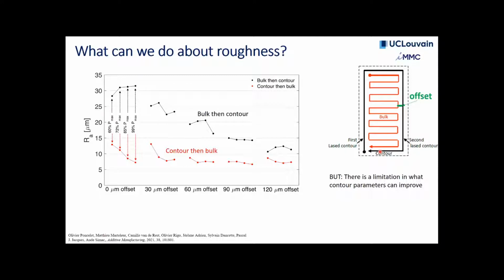to improve the roughness. This indeed is a good solution, and that works quite well. In particular, it's better to do the contour first and then the bulk. We have explained this in the paper. If you're interested, you can have a look. But what's interesting to see is that even in the best conditions, you're still in the, let's say, 5-10 micron range in terms of roughness. There are some papers in the literature where you go down to like 3 microns, but it's really hard to